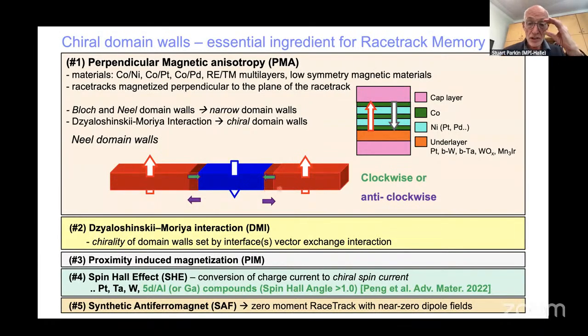At the same time, these domain walls are either clockwise or anti-clockwise. They're chiral domain walls due to an interface exchange interaction between this underlayer, let's say platinum, and the first cobalt layer.